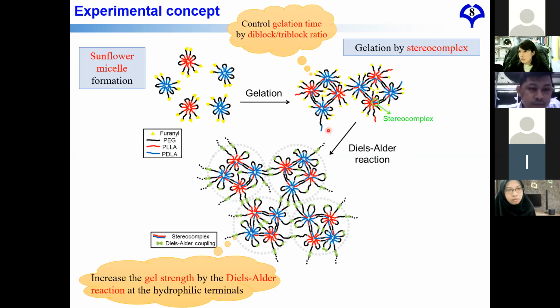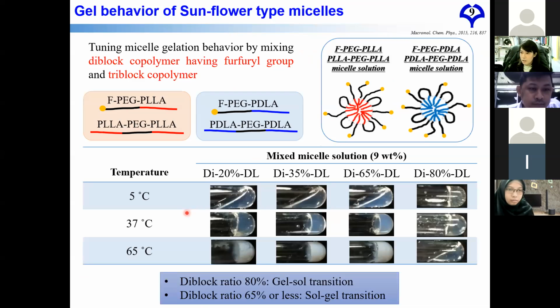So in this experiment concept, we first want to control the diblock and triblock ratio to control the gelation times. And after controlling the gelation times, we can also introduce another reaction to the hydrophilic segment to increase the gel strength. So first, I want to introduce how we can control the diblock and triblock copolymer ratios.